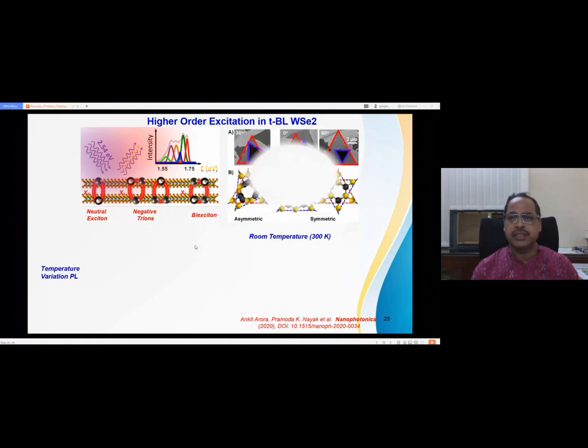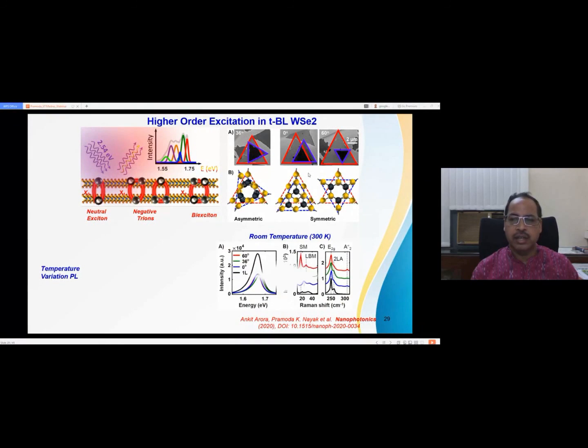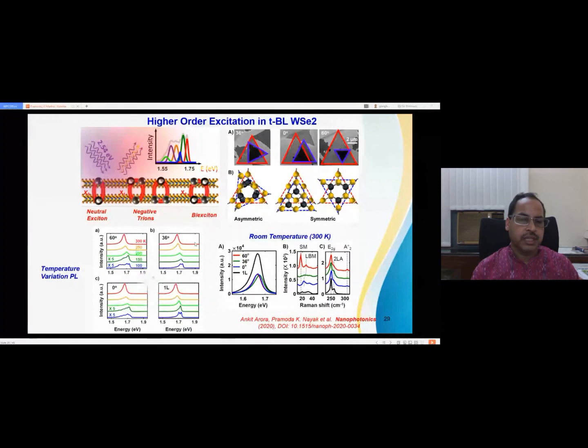So for that we have studied this schematic. We have studied the twisted bilayer WSe2. So here you can see the intermediate angle. This is the high symmetric stacking configuration. This is the schematic and these are the SEM images. We have done room temperature Raman spectra, because in a heterostructure there is PL quenching. And for the high symmetric configuration, we get the shear mode or layer breathing mode. But when you do the temperature variation PL spectra, as you can see, for the one layer and the intermediate coupling it is more or less the same. But for the high symmetry stacking configuration at very low temperature, you can see different peaks are involved.